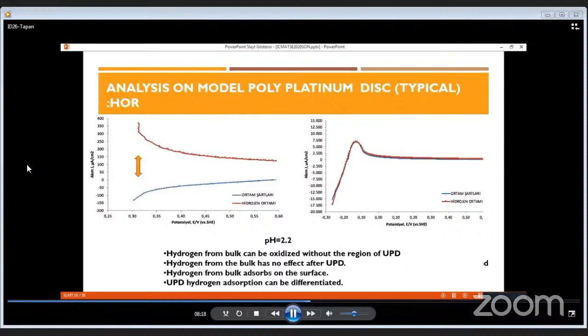During electrochemical tests, in order to understand if the catalyst can be used for both hydrogen evolution and hydrogen oxidation, we have purged hydrogen into the electrolyte and scanned the catalyst at different scan rates, which you can see in the figure on the left. On platinum, the hydrogen formed in the bulk can be oxidized with the scan starting from the positive potential. On the other hand, scanning from negative potential will cause no difference between hydrogen purged and unpurged environments.